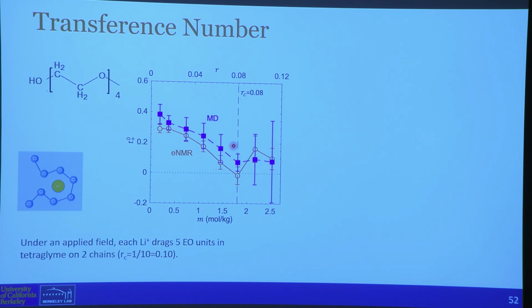And so here is the eNMR data, this weird sort of hump all the way to 0 and then rising up. Those are MD simulations, and this critical concentration is about 0.1. This material is a small molecular weight PEO. It's tetraglyme. It's 4 units because that's all we can easily put in the NMR cell. We can put an 8-mer too, as Julia knows. Yeah, so this is the shape we get.